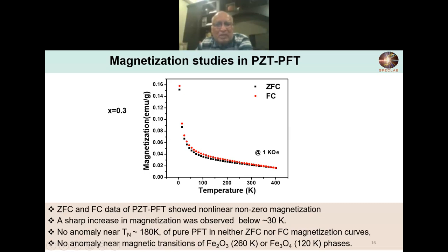Also, we can expect in these materials maybe impurities like iron oxide, Fe2O3 or Fe3O4, which have a transition around 260 and 120. But looking at this curve, there's no anomaly anywhere near 260 degrees or 120 degrees. So we can safely say from all the studies that we are getting that our materials are indeed single phase materials.